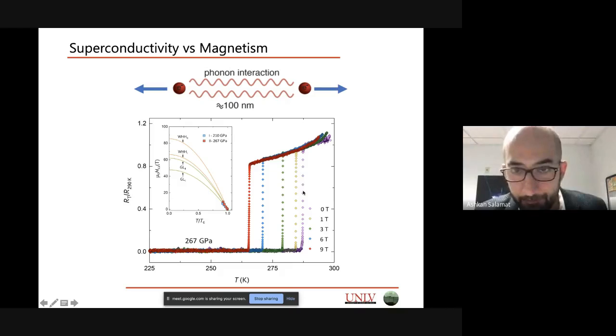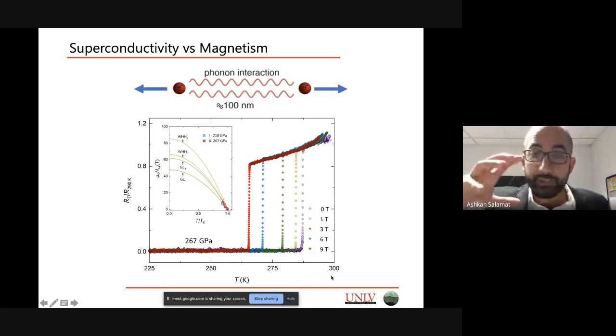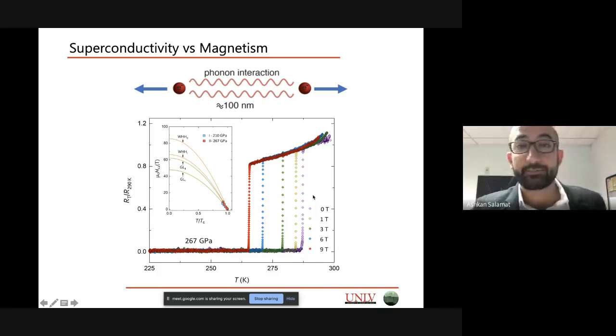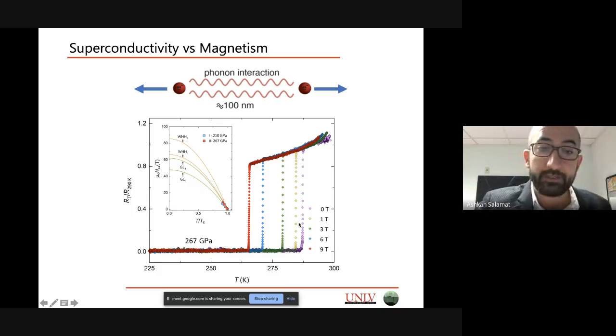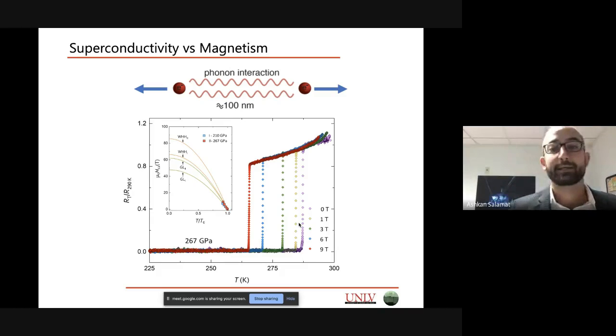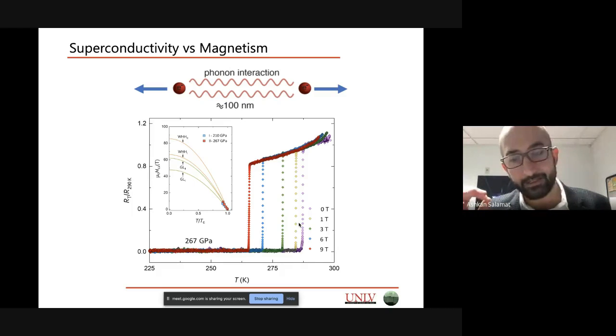The pink or purple is where there is no applied field. So this is the clean superconducting transition with resistance as a function of temperature. And as we increase the magnetic field on the material, this breaks the Cooper pairs, and the superconducting transition temperature gets lower and lower and lower. This is the crowning piece of work. This is what got us all the attention. This is truly indicative of a superconducting transition. This response to magnetism is the true hallmark of this quantum phenomenon.